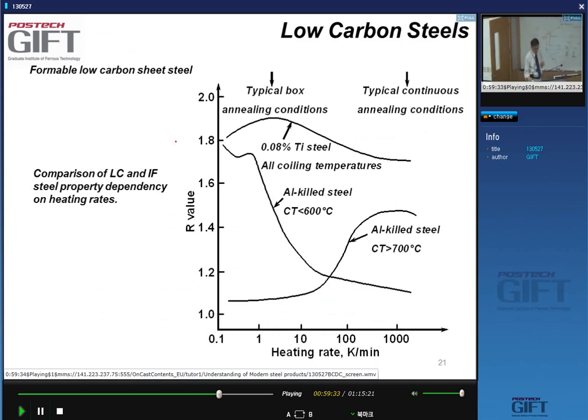So the big difference between aluminum-killed low carbon steels and IF steels is what we call robustness. This is what we call a robust steel or alloy design concept. Why is it robust? Because the properties are not very dependent on changes in processing parameters. So you can process this steel through many different routes and have guaranteed stable properties.